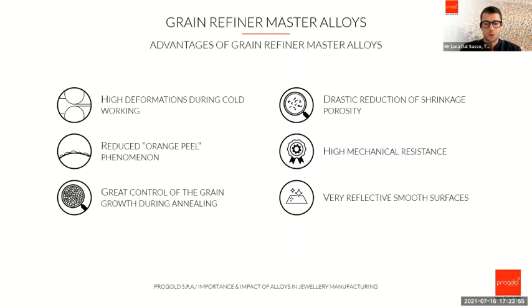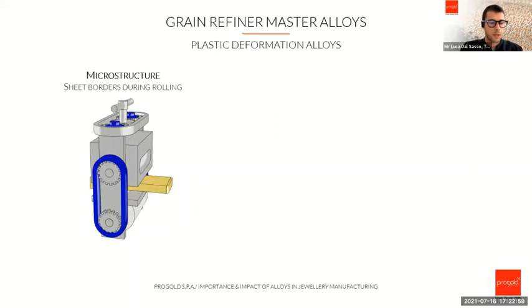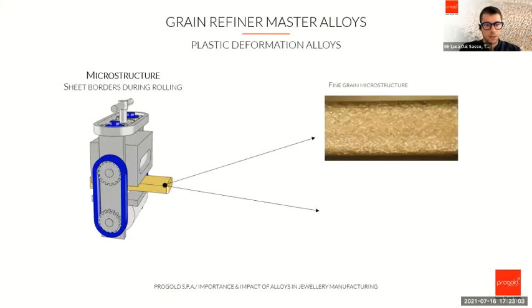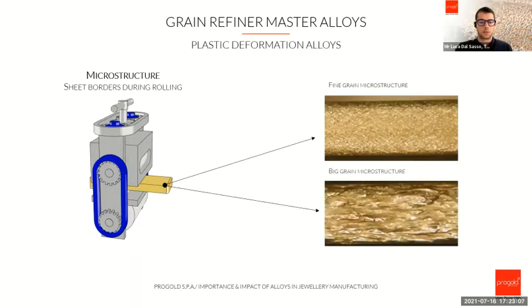So, going on with some images and some more understandable concepts, let's start by having a look at the sheet with a fine grain microstructure and with a big grain one. It's very easy to understand, even with the eyes without the microscope, that the microstructure is completely different. And as you can imagine, on the border between one big grain and the other, it will be easier for the metal to have defects and show cracks. And imagine how many small grains are in the upper microstructure, so how hard will it be to find these defects on a fine grain microstructure?